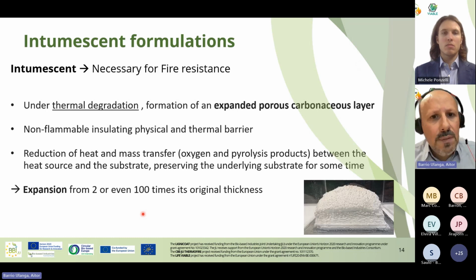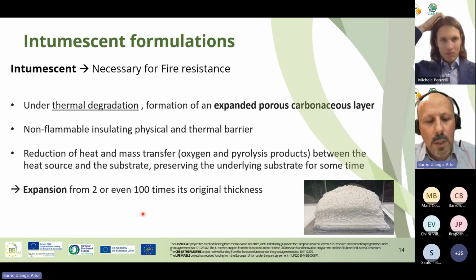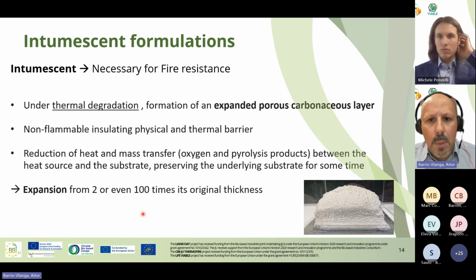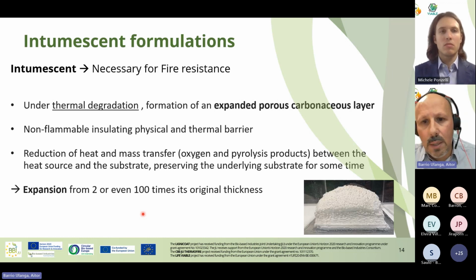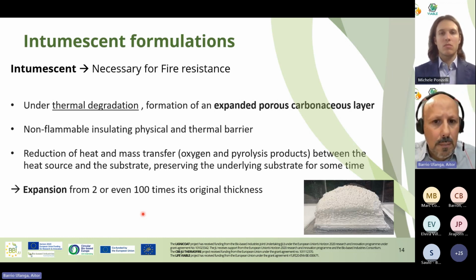There is a special technology for fireproofing, the intumescent systems, which is more focused on fire resistance because it's a very, very effective method for insulation of the material. In the case of fire resistance, we are talking about 1,000 degrees, 1,200 degrees. That is a very high temperature. You need this kind of mechanism if you want to protect the metal or the substrate. So the principle is the formation of an expanded porous carbonaceous layer, and you obtain a non-flammable insulating physical and thermal barrier.